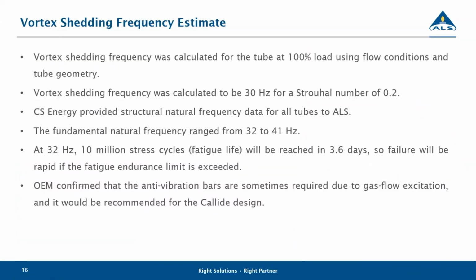We also had a look at vortex shedding frequency. So we looked at the length of that sling tube versus the design gas flow across that tube and calculated the vortex shedding frequency. It's around about 30 hertz for a Strouhal number of 0.2. So obviously there is a range there. We did calculate a range, but for 0.2, it's 30 hertz. And then CS Energy also, during outages, test their tubes for natural frequency to check if the tubes are actually carrying load. So they put an accelerometer on there and then do a bump test and see what the frequency is. The fundamental frequencies that they've measured on site are between 32 and 41 hertz. So we can see that it is pretty close.